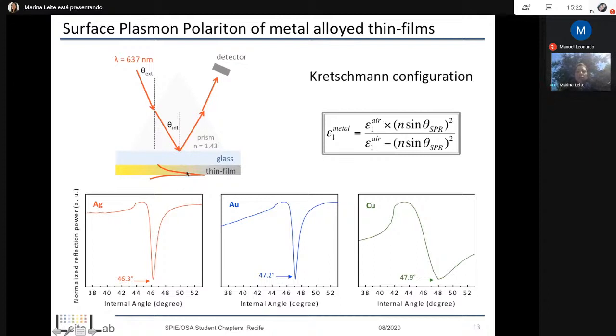So you can see that the full width at half max of this peak can vary quite a bit. For silver, it's particularly narrow, which basically explains why people love using silver in plasmonics despite oxidation of the material. Gold is also very deep. The reason why people don't use gold as much is because it's a material that is considered very lossy in the visible range of the spectrum. When people say lossy, they're referring to gold absorbing quite a bit of light in the visible range. So it's better for IR applications, not the visible range. And copper, which is quite broad, is also a bit lossy and not as well behaved a material.